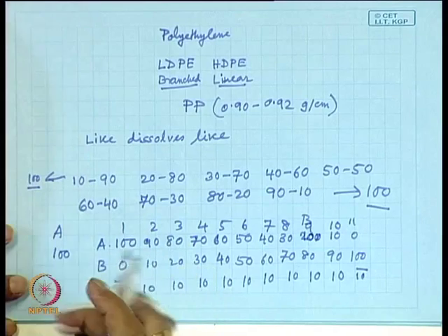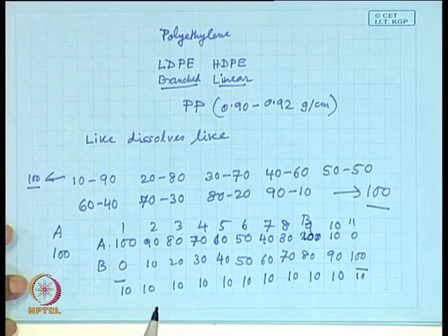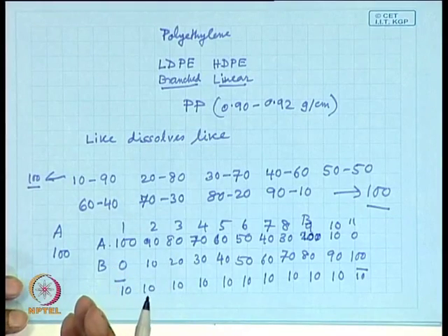You will find certain fractions of solid has come out, and you filter it, wash it, and by gravimetric means you get the fractions of those solids. Then you plot those fractions. Then with the help of other techniques, once you have got a certain quantity of one fraction, you measure its molecular weight by some absolute techniques.